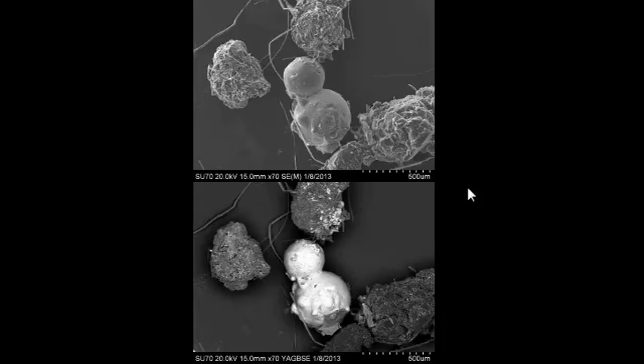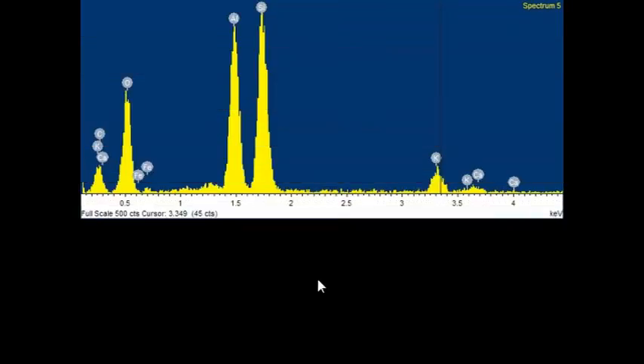Another mode that you can operate a scanning electron microscope in, depending upon your detector, is what's called backscatter mode. So here, rather than looking at electrons being conducted through, we're looking at electrons that are being scattered or reflected off the surface of our sample. And you'll notice that these particles out here don't really change in their appearance, but this inside particle does. And this has to do with the fact that this inside particle is highly inorganic in nature as opposed to these particles, which are very organic. So these essentially are plastics, and this thing is not. So that kind of led us to wondering more about what it was.